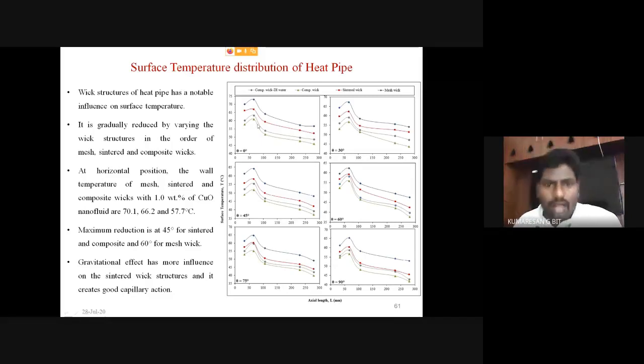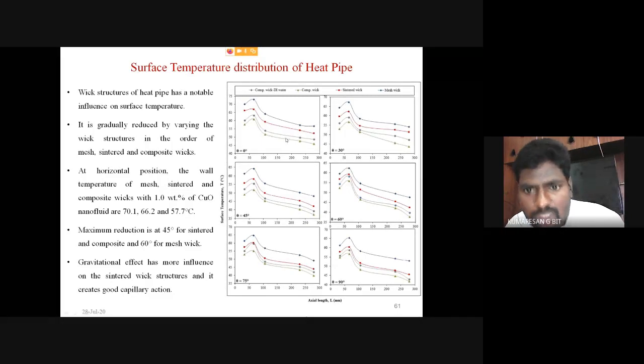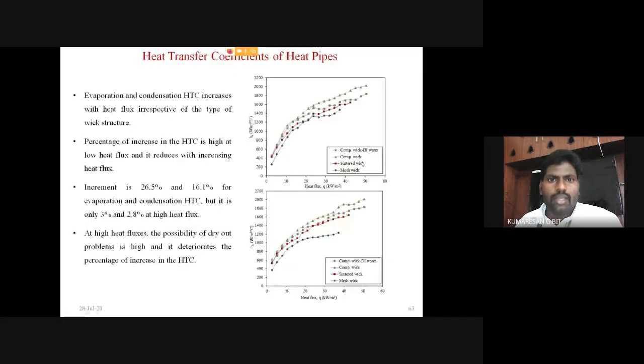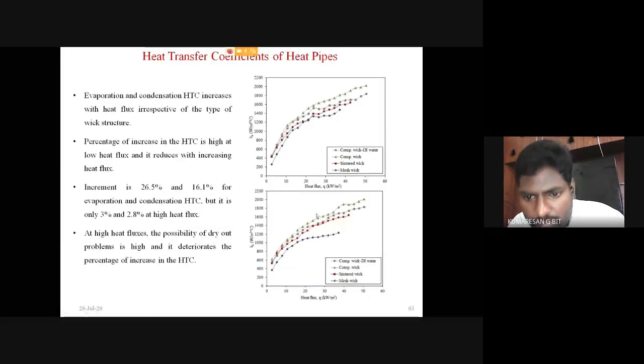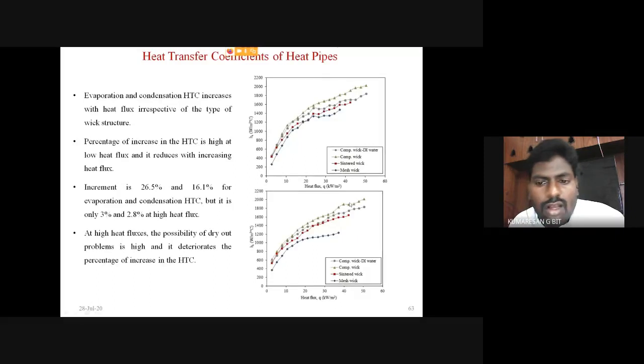graph, the lowest surface temperature was attained by the composite wick with 1 weight percentage in all the figures, you see here. Okay, then HTC of heat pipes operating with a composite wick, that means made up of composite wick and 1 weight percentage of CuO nanofluids, registered the highest HTC value at the evaporator as well as in the condenser section.